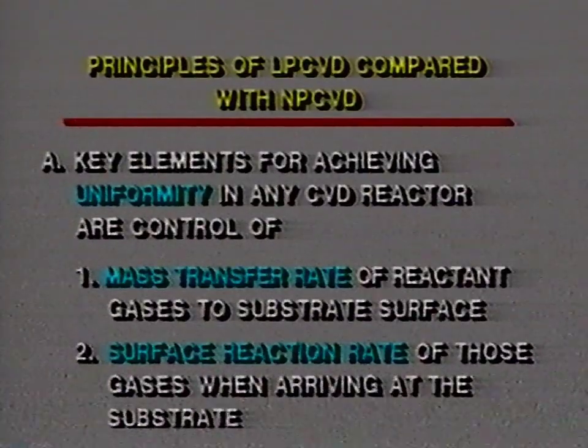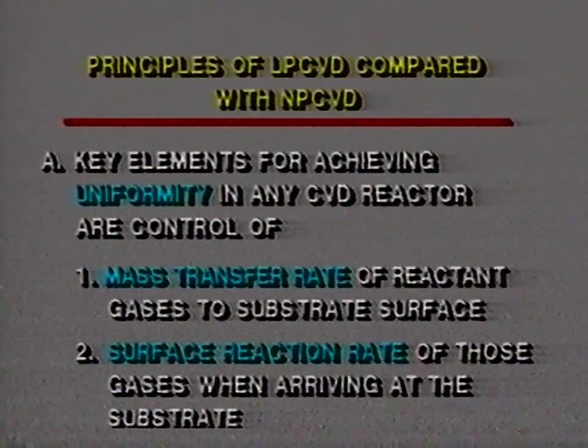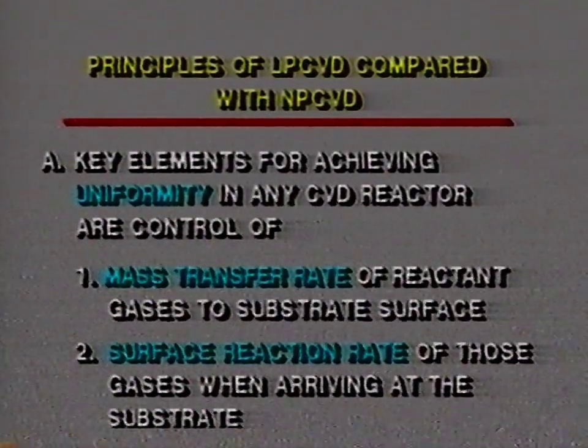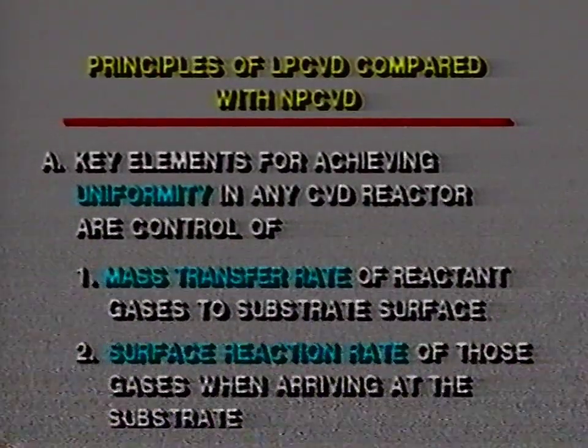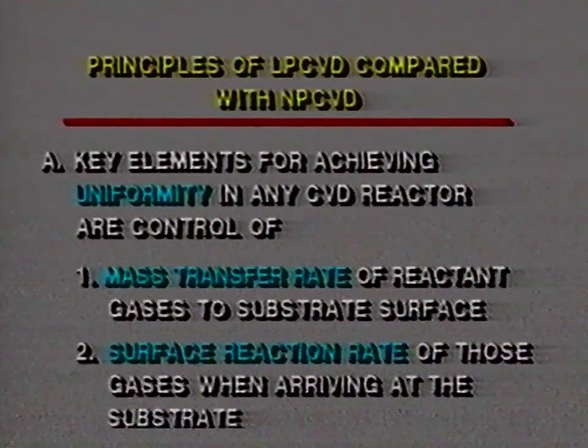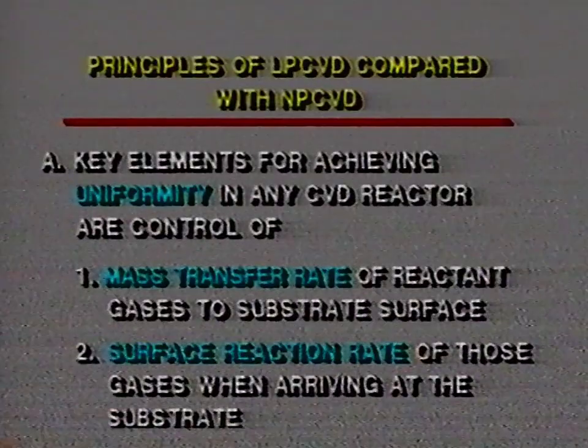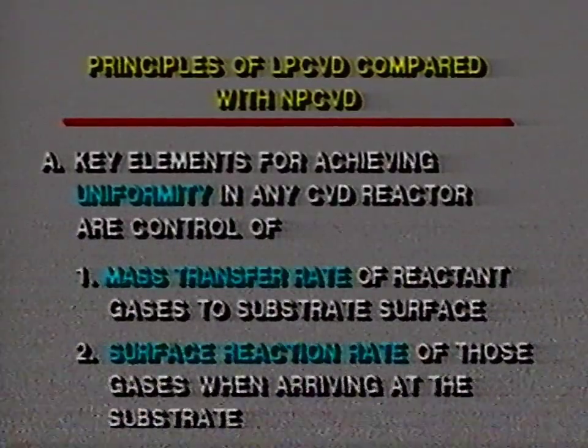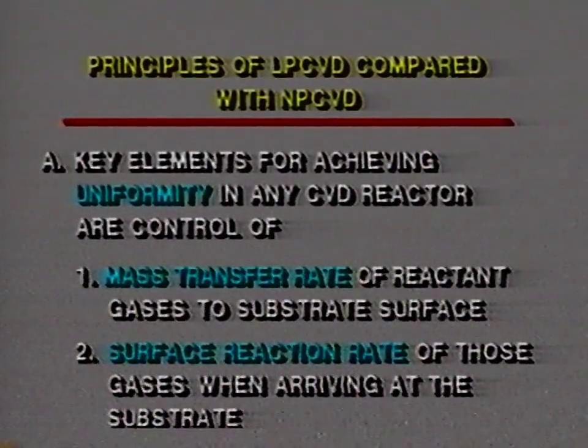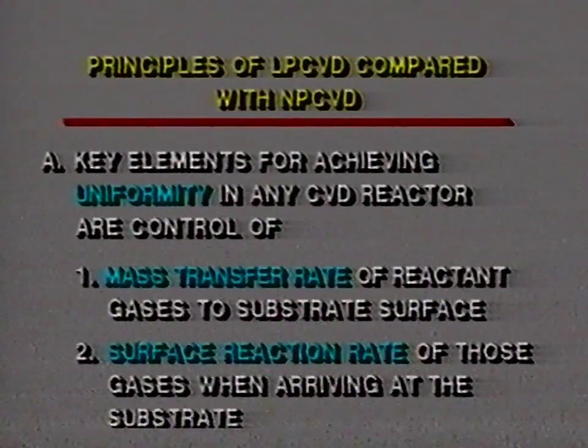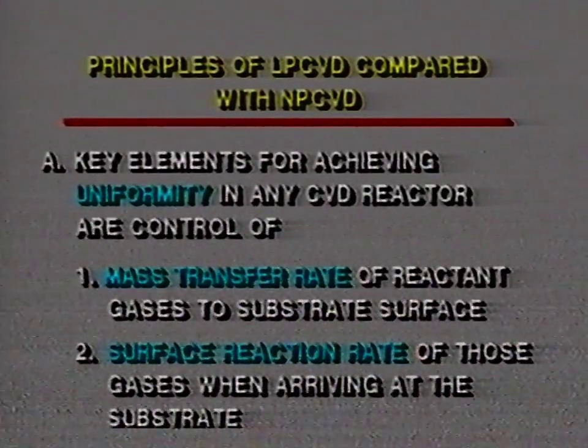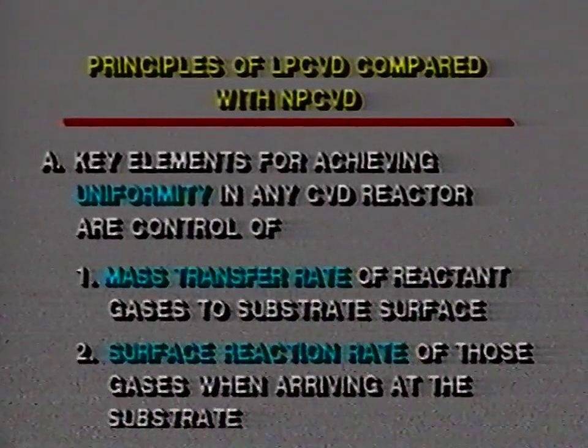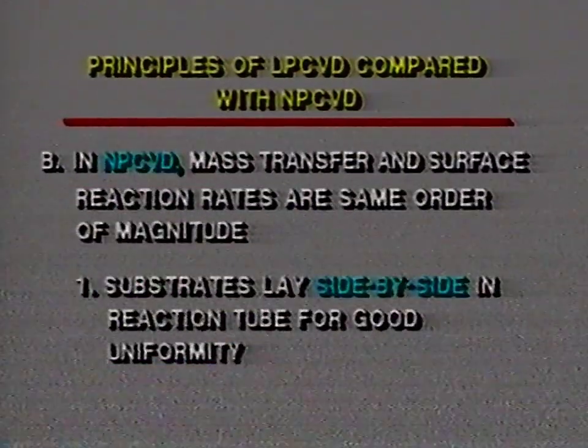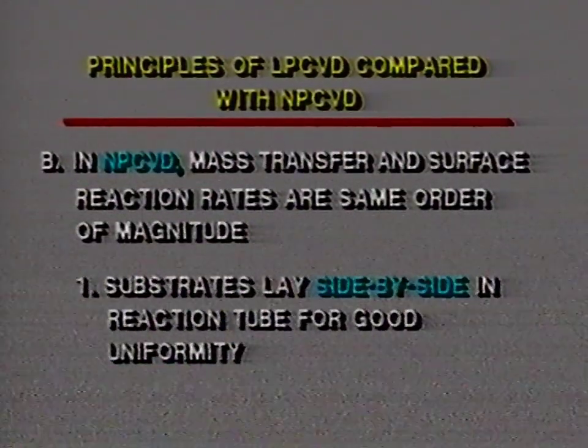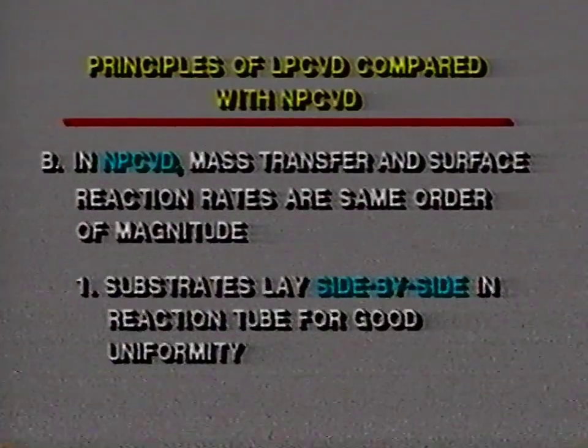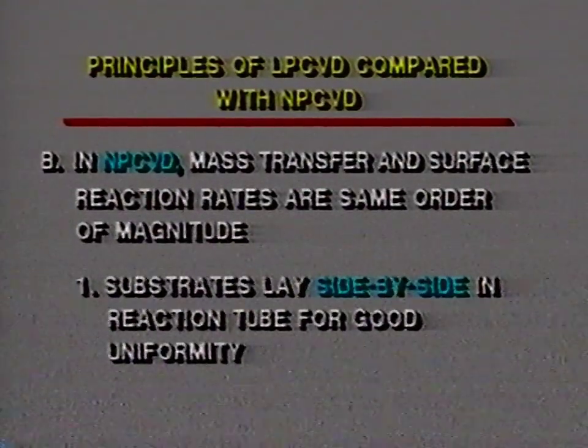Now, the control of uniformity is based essentially on the number 1 and 2, the mass transfer rate of the reactant gases to the substrate surface that has to be controlled, and then the surface reaction rate of those gases once they have arrived at the surface and interact. Now, in normal pressure CVD or atmospheric pressure CVD, the mass transfer and surface reaction rates are essentially the same, or at least in the same order of magnitude.